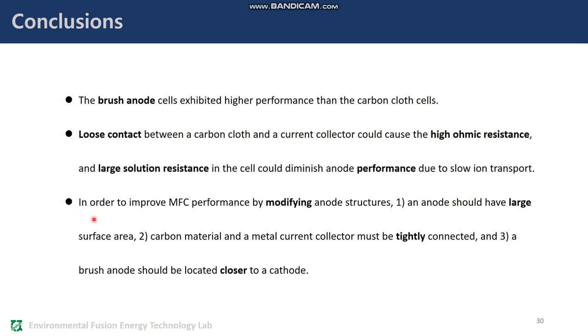In order to improve MFC performance by modifying anode structures: one, an anode should have large surface area; two, carbon material and a metal current collector must be tightly connected; three, a brush anode should be located closer to a cathode.